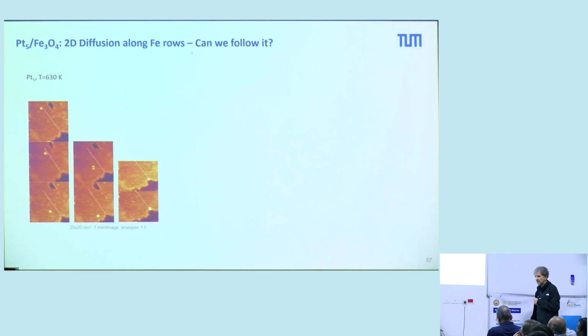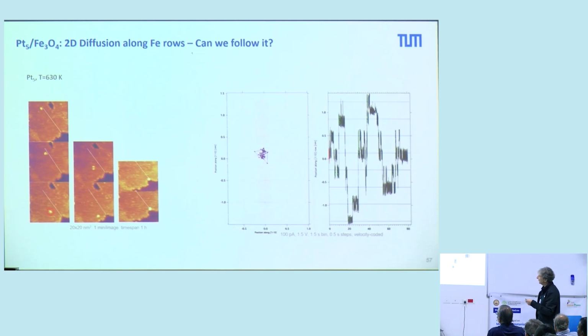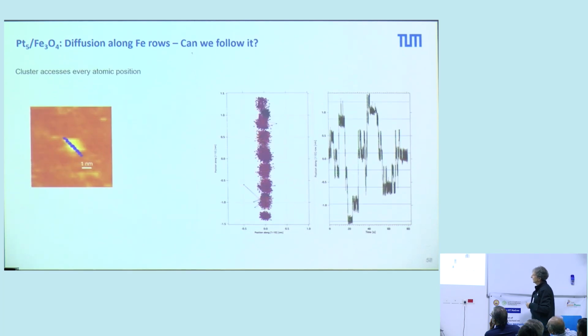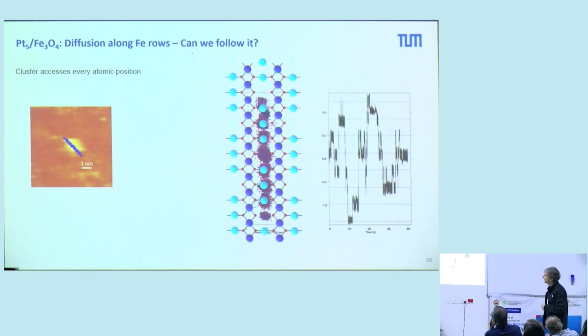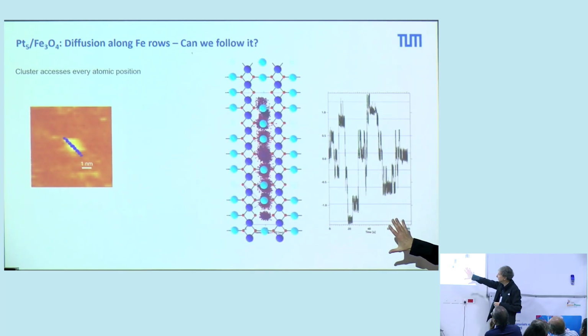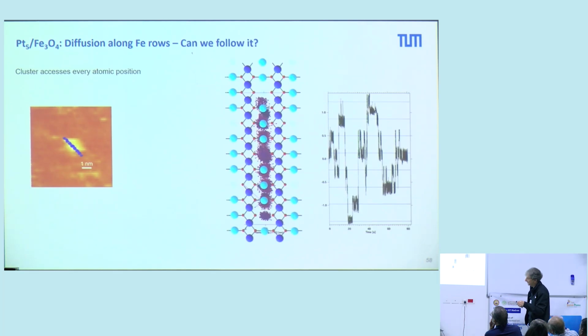Now the question is, can we follow a cluster? Can we use an STM tip and follow the cluster during its diffusion? And for this, we developed these atom tracking methods with which we can do this. And you see here a platinum 5 on iron oxide. And then we start to track this cluster. And you see that it migrates along the row. These are the residence times of this cluster on the surface. And interestingly, if we now put the iron oxide lattice on this, you see that it does not discriminate these iron vacancies. The residence time is always the same.